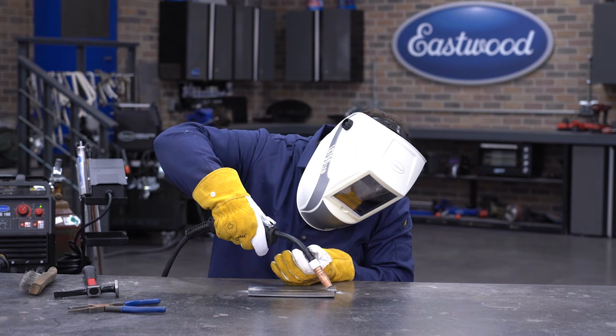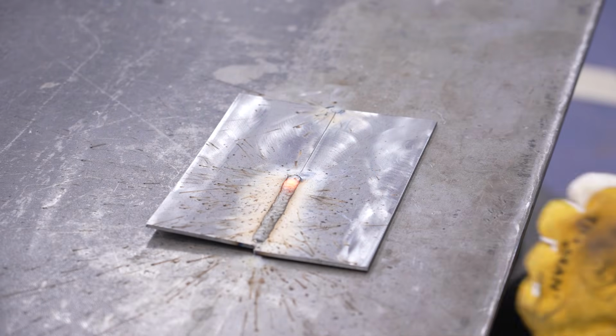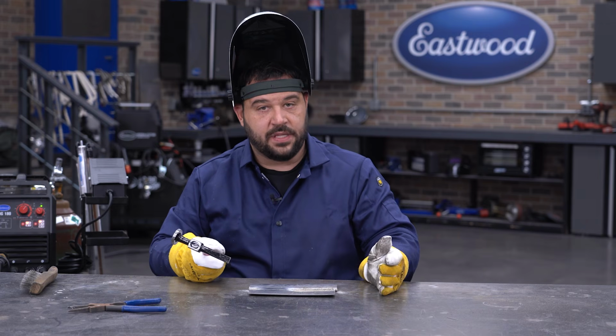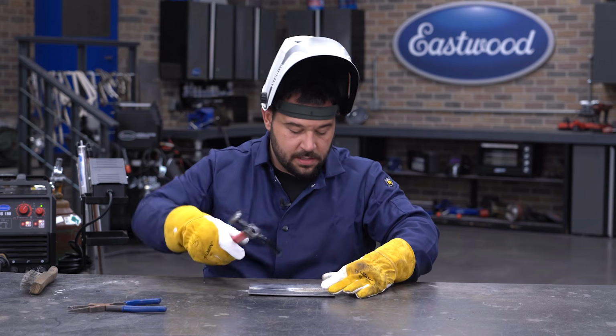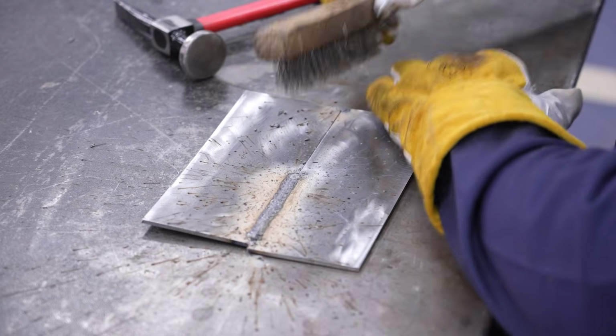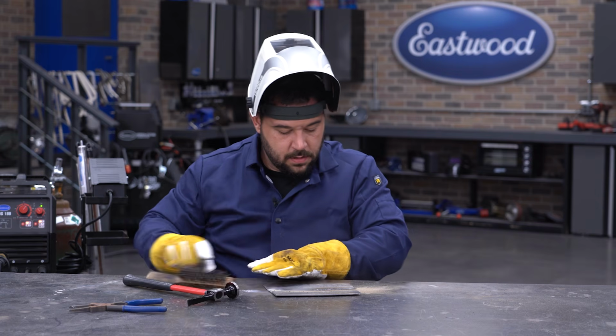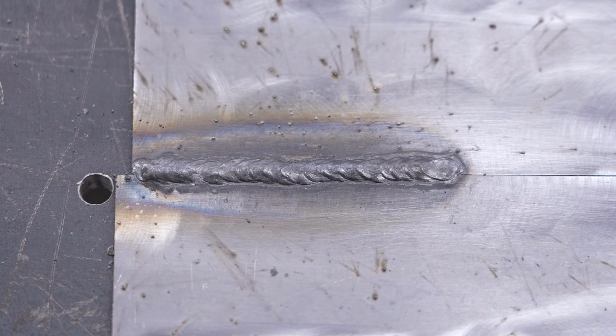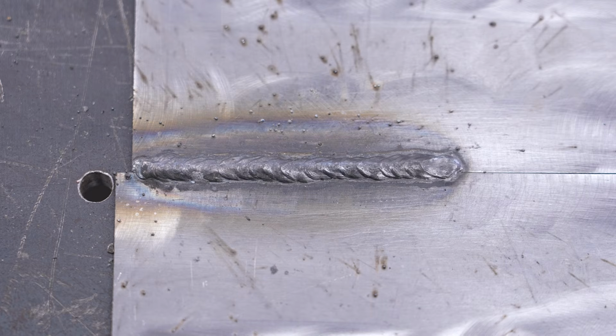So again, we're arcing up right here. Once my puddle's established, I'm splitting the cursive E over the weld joint, half on top, half below. And we're just keeping this consistency throughout the weld. Once we've terminated our weld, we can scratch the flux off the top and we'll be left with what we've just created here. Take your wire brush, clean it up. And there you have a proper weld joint with Flux Core.